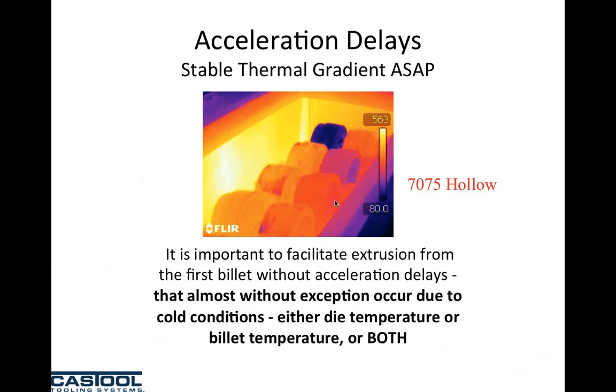What you want is, starting from the first billet, there's no delay in acceleration of the run speed. So the temperature of the die coming out of the die oven has to be perfect, and also the billet temperature has to be perfect. Both of them have to be controlled in relatively tight temperature windows.